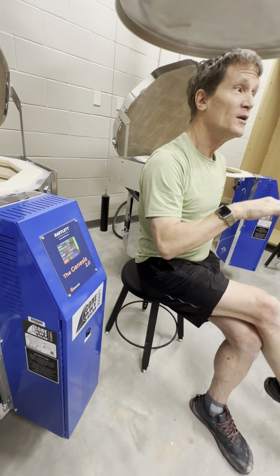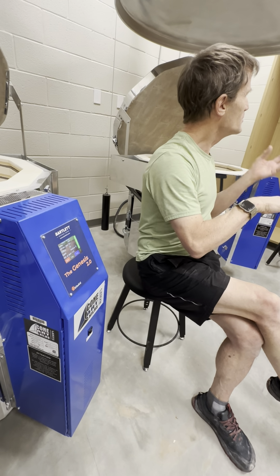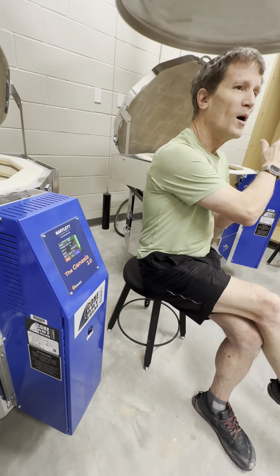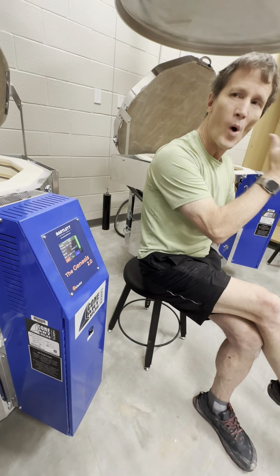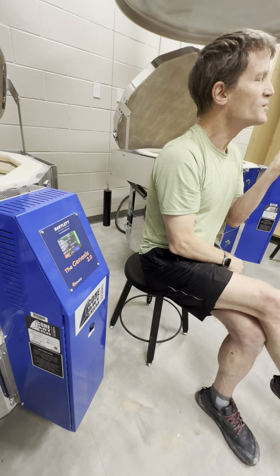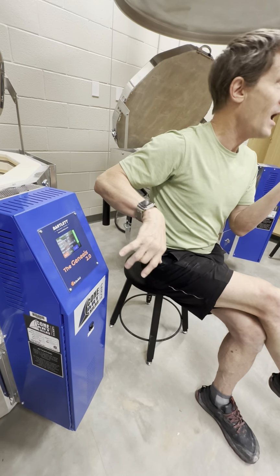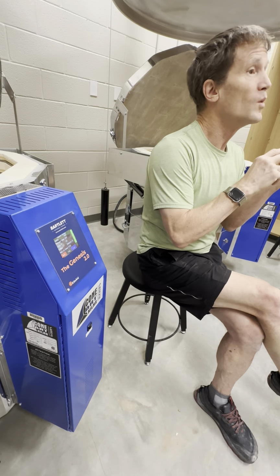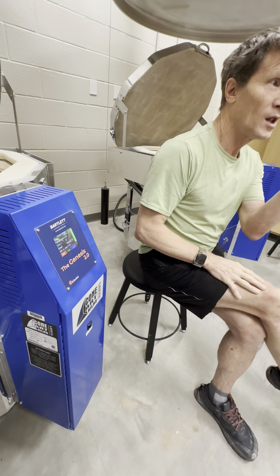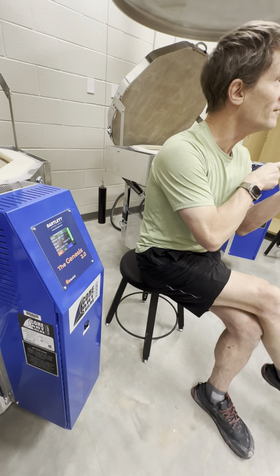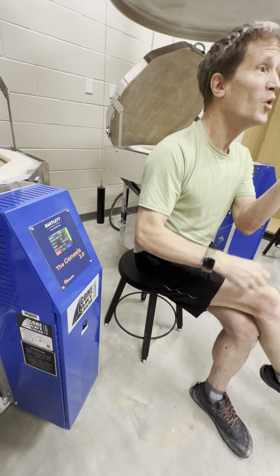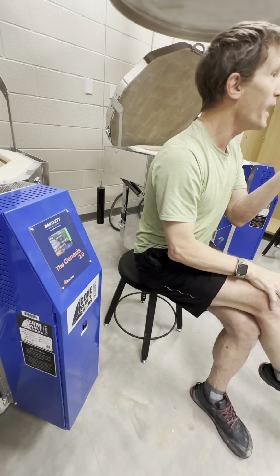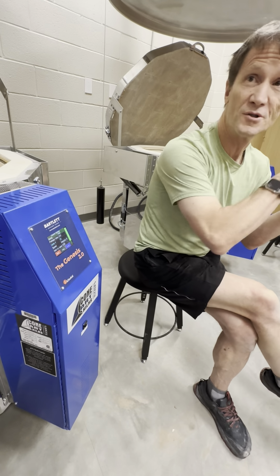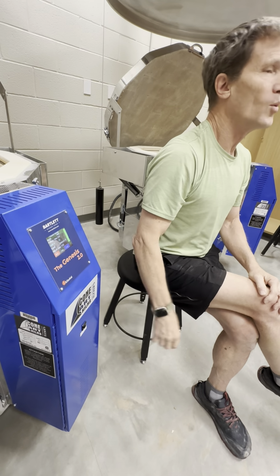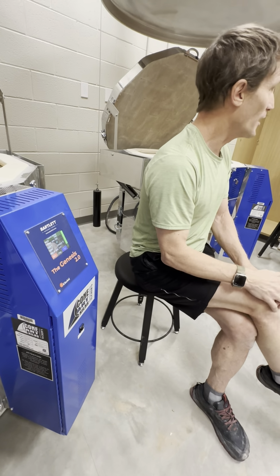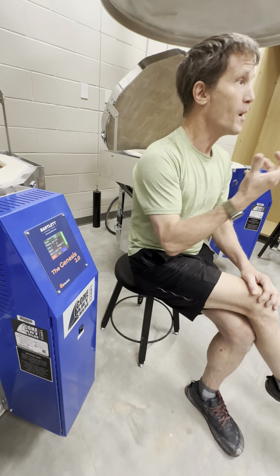So if we're firing to O5, the reason why that bottle of glaze says to fire to O5 is because the moisture is going to suck into that ware at cone O5. If you accidentally fire it to cone 5, it's going to be much more vitrified, and the clay is not going to accept moisture like it would at O5. You could put 10 layers on there, and it's not going to dry. The moisture is not going to be sucked into the ware, so it won't accept glaze. Does that make sense? Okay, so that's why we fire to the temperature that bottle says.